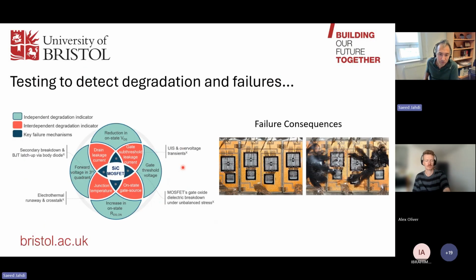Now, in terms of reliability as well, we need to be very careful. There are very severe consequences for failures, but there are degradation indicators. Some of them are independent, some of them are interdependent. By condition monitoring of the performance of the devices and observing some of these key parameters, you will be able to tell whether the device is degrading toward failure and whether there is something you can do to prevent that. In EVs, we call that limp home mode: if you detect that your devices are degrading, you can reduce the power consumption, so electrothermal stress will be reduced, and you just deliver enough to reach home, and then take maintenance and closer observation of what's happening with your devices at the heart of your drivetrain.